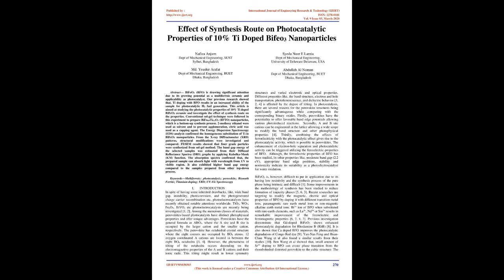The conventional sol-gel technique was followed in this experiment to prepare BiFe0.9Ti0.1O3, BFTO, nanoparticles, which is a bottom-up synthesis process. 2-methoxyethanol was used as solvent, and to prevent agglomeration, citric acid was used as a capping agent. The energy dispersive spectroscopy, EDS, analysis confirmed the homogeneous substitution of Ti in BiFeO3 nanoparticles.